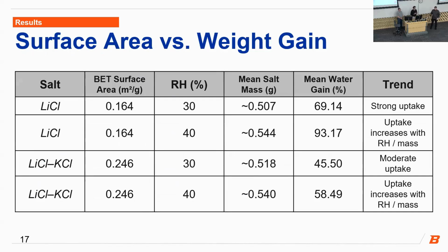And finally, we have our surface area versus weight gain. This table correlates surface area with relative humidity with the dry salt mass. And there's 2 main points that we can take away from it. The first point is, as you would expect, with increasing relative humidity and increasing salt mass, there's an increase in the mean water gain. But the second and more important part is, as you can see, the eutectic has a higher surface area, but a lower water gain. That tells us that for the surface adsorption portion of this process, the surface area is really important, but once the process transforms into bulk diffusion, the salt composition itself is the driving factor in this water uptake.